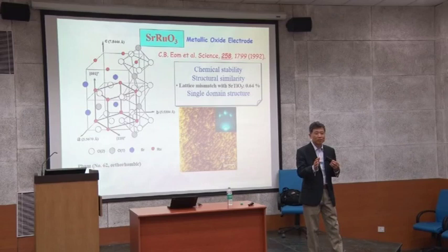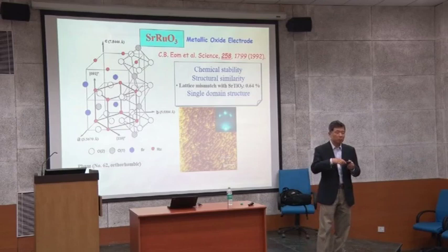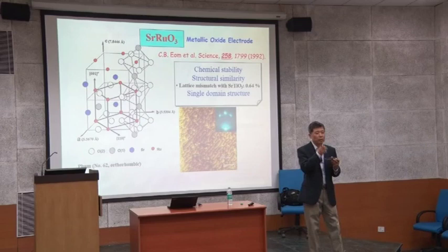Okay, to do that, you have this problem. The substrate is cubic, what you're using. Like most people use a strontium titanate substrate as a cubic material. And for a cubic substrate, you look at the four-fold symmetry. It looks like this direction and that direction are equivalent. But the film you are growing has two-fold symmetry. This way and that way are different.